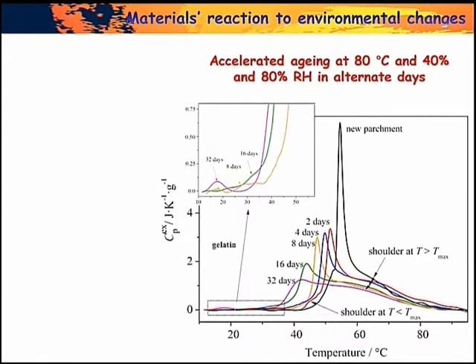Here is one example, a series of parchments that were exposed to 80 degrees Celsius and alternate relative humidity, 40% and 80%, in alternate days. And you can see that the shape of the peak and obviously the parameters characterizing these peaks change dramatically with increasing time. Also, the gelatin is formed. You can see here in the zoomed area.